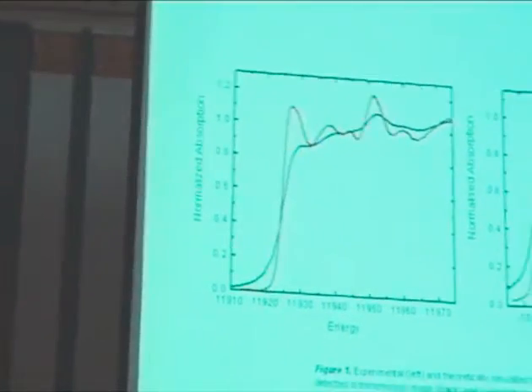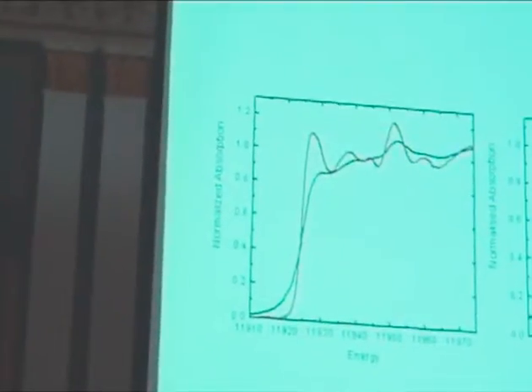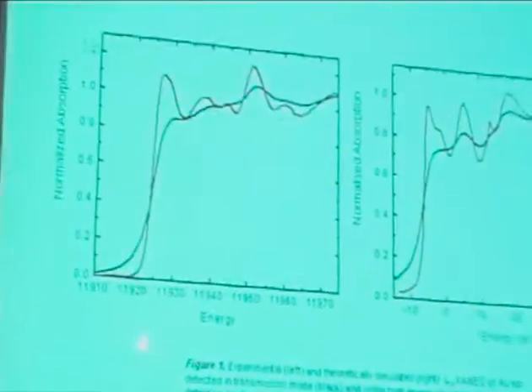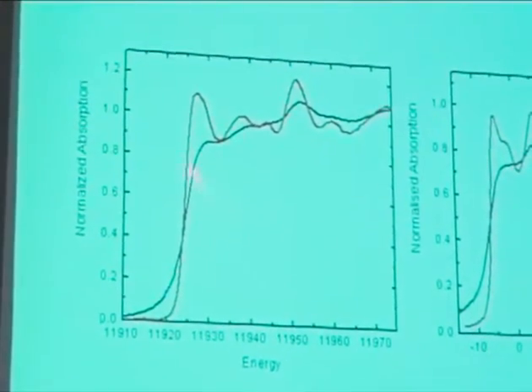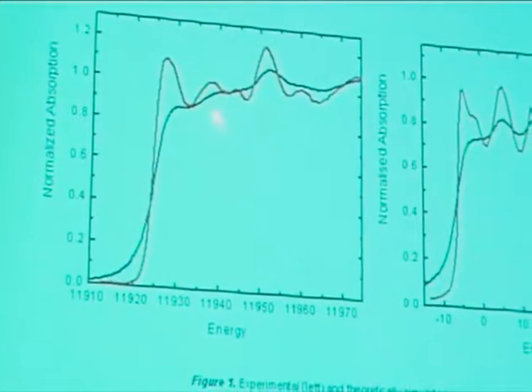What I've shown you until now is normal EXAFS. We have our sample, the X-rays go through, we have an ionization chamber behind the sample which measures the intensity of the X-rays. So you measure the absorption of the X-rays. So what you do is you kick out an electron from a deep level, it goes to infinity, and you leave a hole in a deep level. Now the deeper this level, the quicker it fills. So the lifetime of this hole determines the line width of your spectrum. This is Heisenberg uncertainty principle. So here we are talking about, as you see, 12 kiloelectron volts, 12,000 electron volts. That's quite deep. So the line width is 1, 2 electron volts. And that's why it smears out.